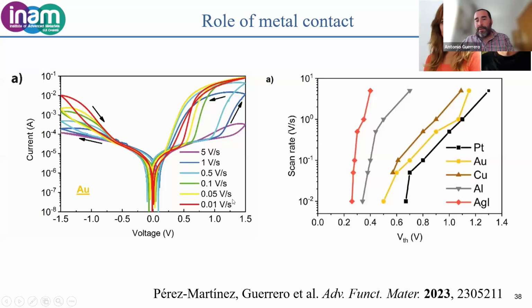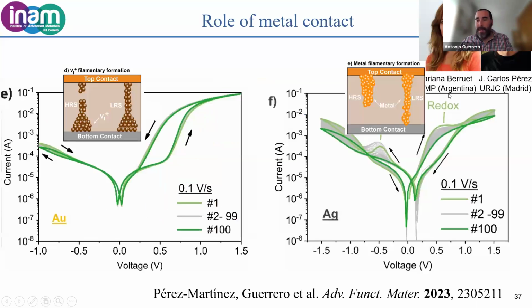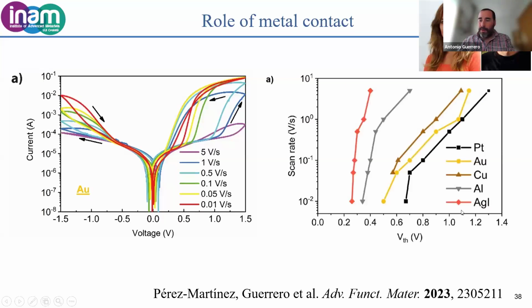The reason why we need this type of electrochemical reaction is that if we are to make filaments of metal coming from the top, the metal ions will need to follow the electrical field. And if the metal is in oxidation state 0, not charged, then it cannot follow the electrical field. So if we want the ions to move, they need to be oxidized. This is why the system works so nicely when we use silver already oxidized. The silver can follow the electrical field because it's already pre-oxidized.